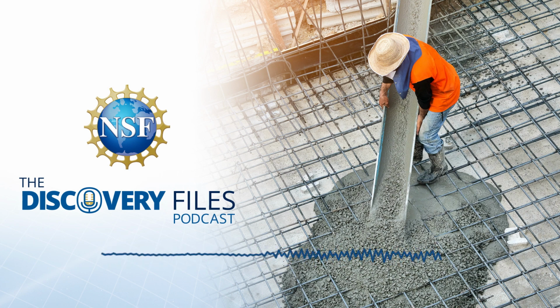I talked about the raw powder of cement, manufacturing of cement, the clinker, and then we shifted to concrete. But to be able to have that reaction, you take the clinker powder, you add water, and then you have the aggregate. Now, when you have the clinker powder and the water, then the raw grains are going to react to form calcium silicate hydrate. So you have that hydration reaction. And then you have different building blocks, low density versus high density calcium silicate hydrate. It's almost like the DNA of cement, if you want.